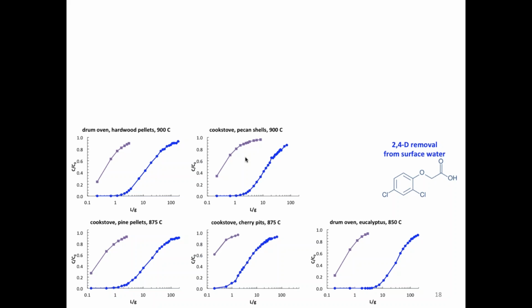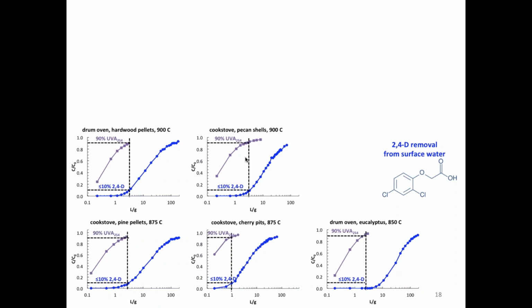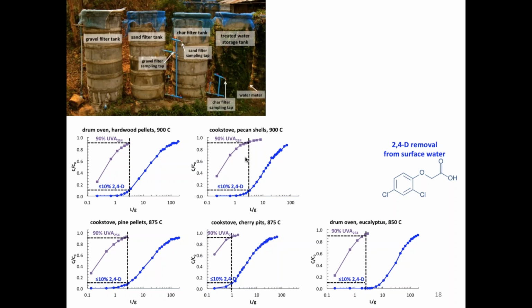And what we saw is that with these high temperature chars, whenever you reach about 90% UVA breakthrough, your 2,4-D breakthrough is at about 10% or less, approximately speaking, under these experimental conditions. We saw that consistently for different scales of biochar production as well as different materials, as long as the temperatures were high. That suggests this UVA measure could be a field measurable proxy to allow us to evaluate the real world performance of our systems.